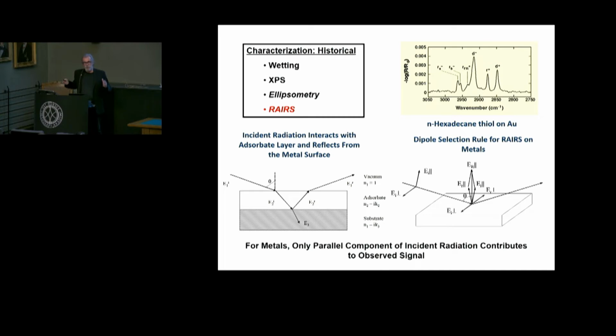Beer's law should kind of work in an isotropic medium. And the point is that there are special projections of these functional groups on the optical axis that's defined by the metal substrate. So when you're doing a reflection experiment, the graph in the lower right-hand corner illustrates that the only intensity that you see comes from projections in the surface normal direction for an incident beam of infrared radiation at a grazing angle of incidence.